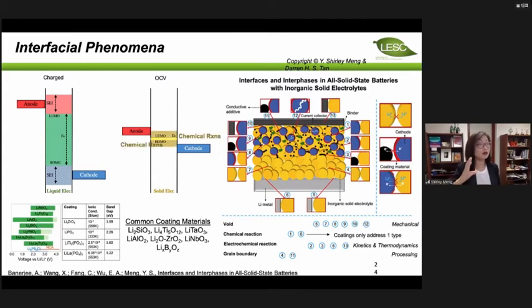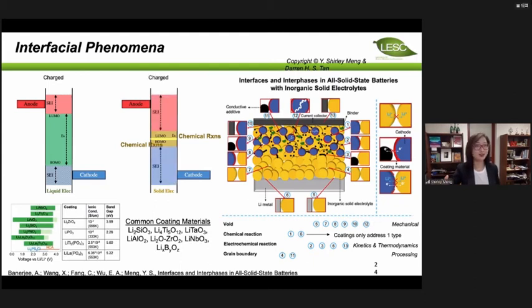Lithium is indeed stable with LLZO, the garnet type of solid electrolyte, but that's a very rare case, right? So number one, material scientists have to think about how to make them chemically compatible to stabilize the lithium metal anode in the solid. Number two, of course, you have another challenge. The solid usually has a very narrow electrochemical window, so you still have the SEI challenge. Number three, the more problematic one for solid is that in the liquid cell, the liquid can flow freely. Whenever you have something, the liquid will flow in.